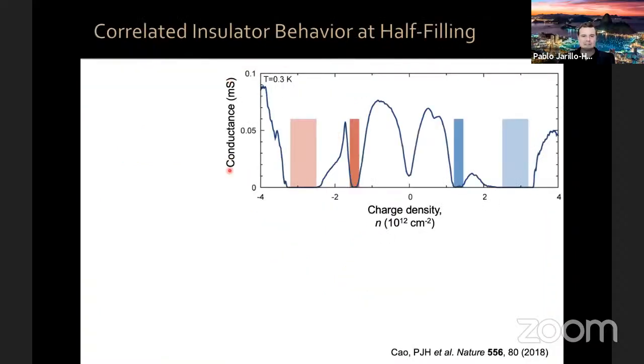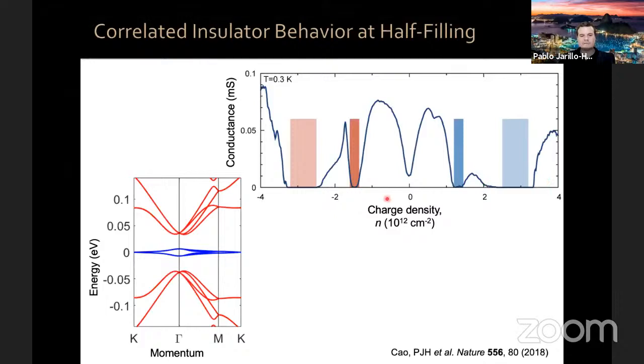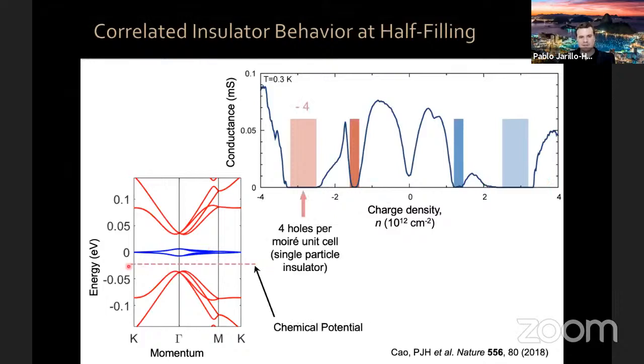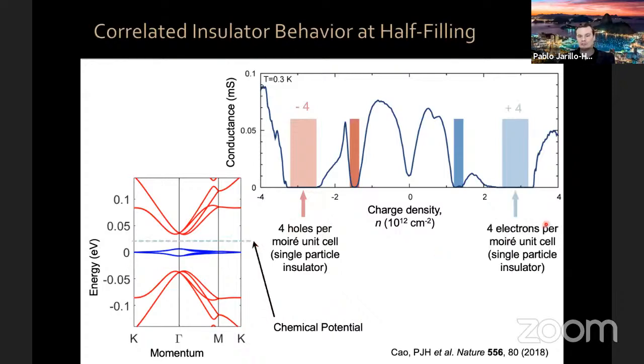So this is data of conductance as a function of charge density in our system. Let me guide you through this data. If your chemical potential is here in the middle of this gap, that corresponds to adding 4 holes per Moiré unit cell. Because this is a single particle gap, we have a band insulator, and therefore your conductance is 0. These flat bands can contain up to 8 electrons per Moiré unit cell. So if instead of minus 4 holes we go to plus 4 electrons per Moiré unit cell, again our chemical potential is in the middle of this band gap, and we have 0 conductivity.